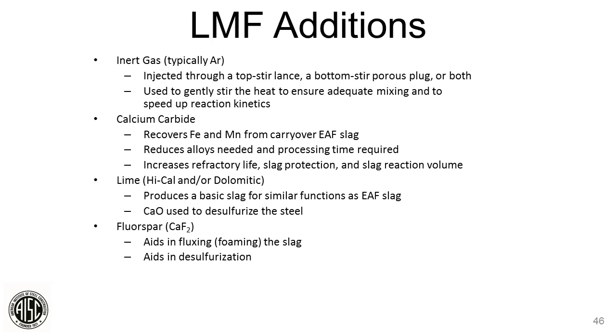So I have multiple additions we do at the LMF. The first one, of course, is the inert gas, typically argon. So we're going to stir it with argon on the bottom. Sometimes you can top lance it, but that's kind of an old practice. Typically now it's all done by bottom stir, porous plug. And at the end of the process, we usually gently stir the steel to float out some of the inclusions.